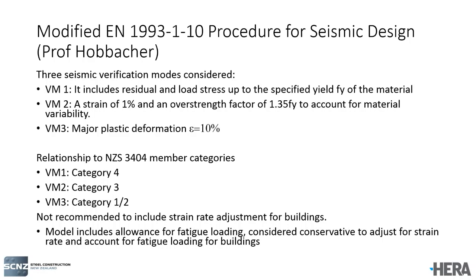We also can consider a temperature shift, and we actually included it in the paper, temperature shift due to seismic strain rates. So if you know your seismic strain rates, the temperature can be shifted to account for those rates. But we don't recommend any shift unless you really need to do it, because I think the requirements are reasonably conservative without any shift of the temperature. Next slide, please.